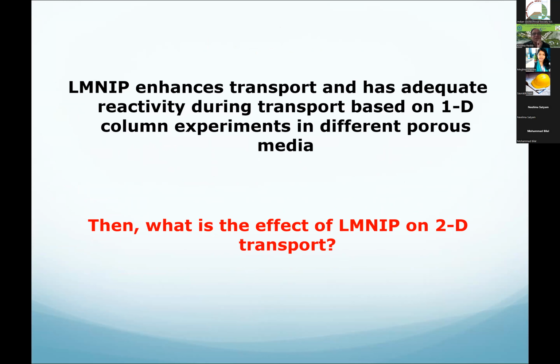Now, that is a column experiment, right? If you are just doing the standard experiment, 1D column experiments are fine. But these particles have a density, right? So you may have particles trying to transport along the flow direction, but they are denser than water. They may be trying to settle down. So this is a 2D effect, and we want to know that one. If you do the small column experiments vertically or horizontally, you're not going to see that 2D effect. So what is the 2D effect?